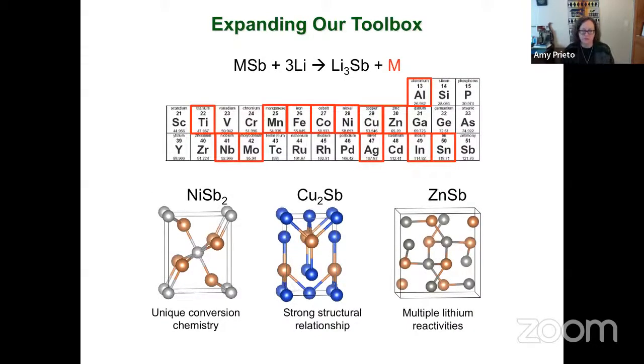I just want to spend 1 minute telling you the direction the group is going in now. We're focused now on looking at other antimonides and also other intermetallics that can balance different kinds of reactivities. All the elements I'm circling in red here follow the general reaction shown above, but they do have very different chemistries. Zinc antimonide, for example, both zinc and antimony lithiate. And so we're looking at the effects of electronic structure, mechanical stability, and chemistry in contact with electrolytes to determine whether or not we can expand this to other areas.